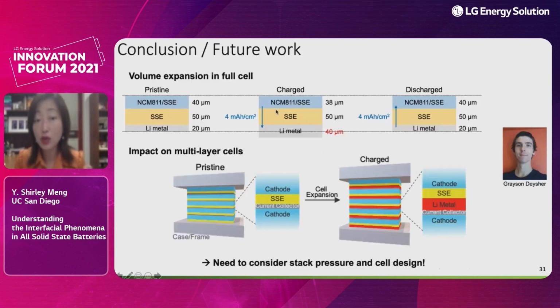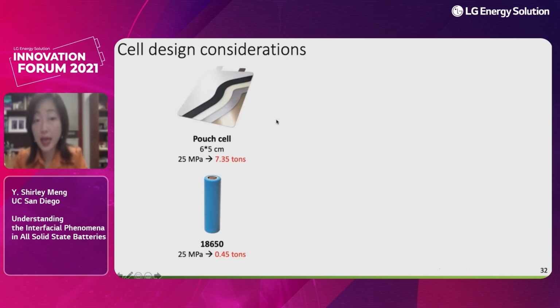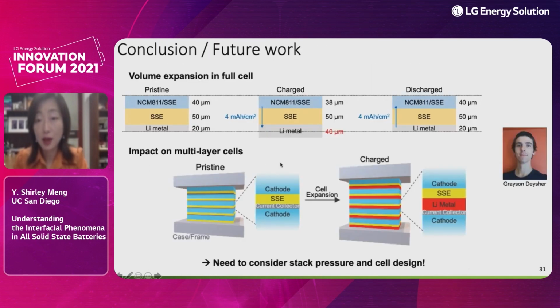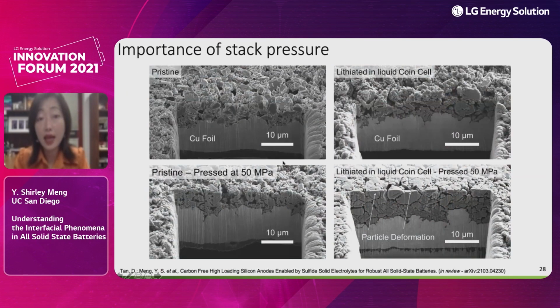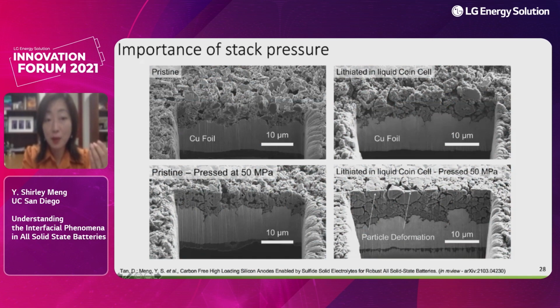Because micron size silicon is mechanically very, very stable, right? So if you look at the pristine materials after 50 megapascal, you take a look at the interface of the solid electrolyte versus the silicon.